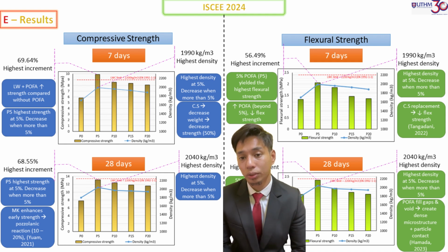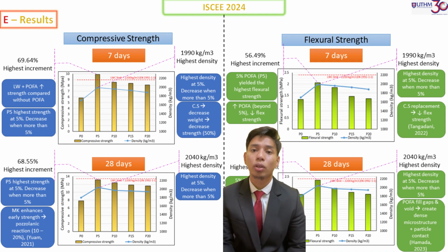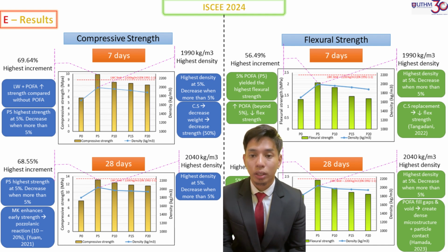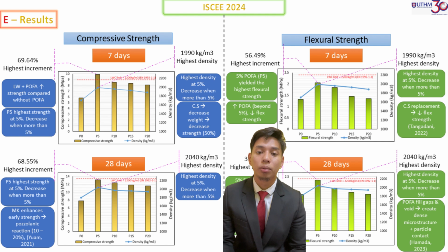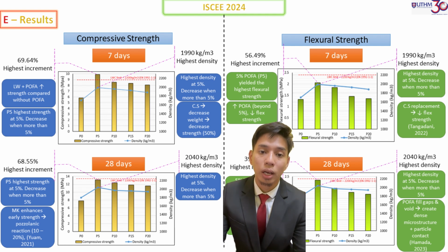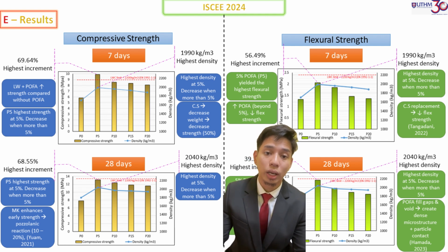The same pattern is recorded. The highest compressive strength is recorded at P5 with an increment of 68.55% from the P0. The Metakaolin enhanced the early strength with the pozzolanic reaction, which ranges from 10 to 20% of partial cement replacement. And the highest density is also at the P5.